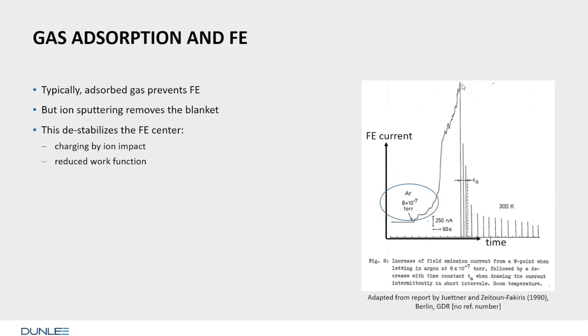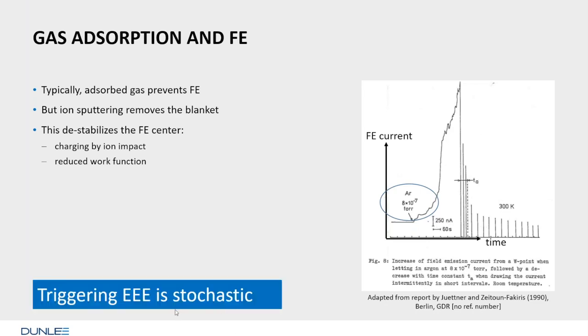So why was that? His explanation was, hey, there is gas on the surface of my tungsten tip. And as soon as I remove the gas layer by sputtering with argon, then the field emission center starts sending out electrons. So there's a blanket of adsorbed gas, which is fine, but it's not stable. Once you sputter it away, field emission rises. So this is triggering then EEE as a stochastic effect. Is there another proof that his theory is right? Well, he turned the valve off, turned the argon off, the pump pumped it out, and then he measured field emission again.